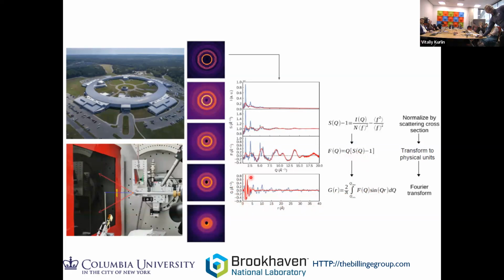So this is some kind of very short range order material. You see it's very flat out here. So this means that our material has asymptoted to a uniform density at high R. What we're always doing is sitting on an atom and looking at our neighbors, and far out in the distance, we just see the average density. But as things get closer, we see hills and valleys and greater and lower probabilities of finding neighbors.